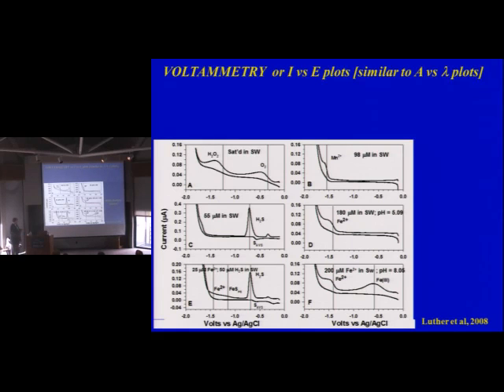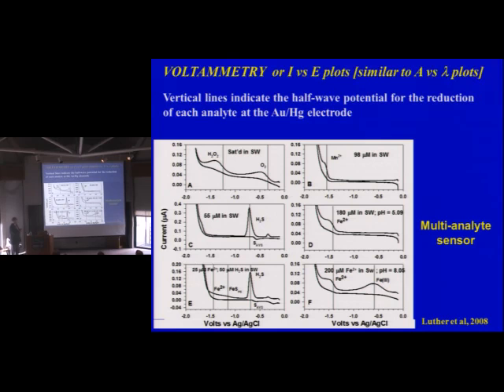What you're going to see here is that this is a multi-analyte sensor, because you'll see here's sulfide. Sulfide's a film former on the mercury. So it forms mercury sulfide, and you destroy that film, and you get a nice sharp peak. So immediately you can see that the shapes are different, which immediately lets you know that you can discriminate them. But what's interesting about all these is that every time you see a vertical line, that's either the half-wave potential or the peak potential. And that means that either an oxidation or reduction reaction has occurred, and it's specific for that analyte. So if you look at energy and counts, each element has its own energy, right? And so you can discriminate it. So that's how we discriminate the species.